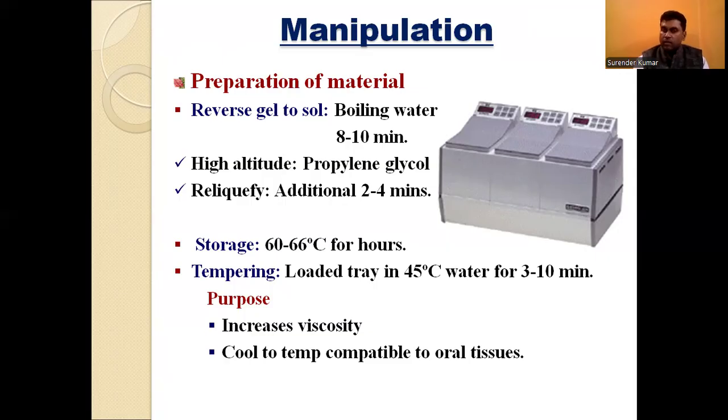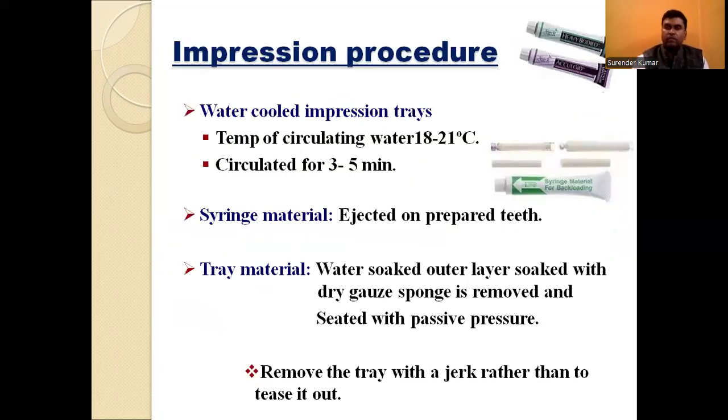Over there, you have to load, and the loaded tray is placed in the tempering compartment, which has a temperature of 45 degrees centigrade water. For 3 to 10 minutes, you're going to place it. The purpose of this is to increase the viscosity and cool the temperature to the oral temperature, so that it can be compatible.